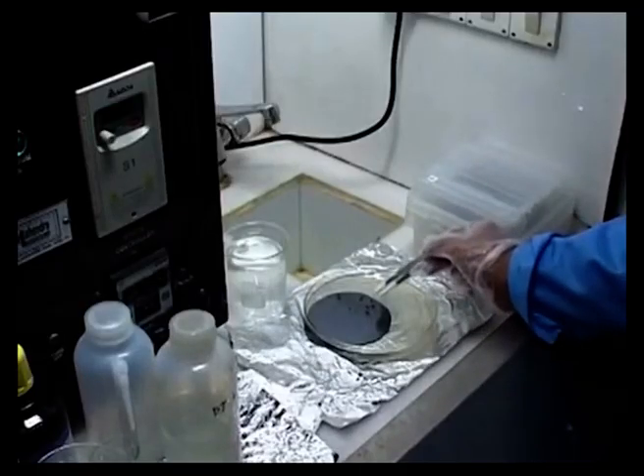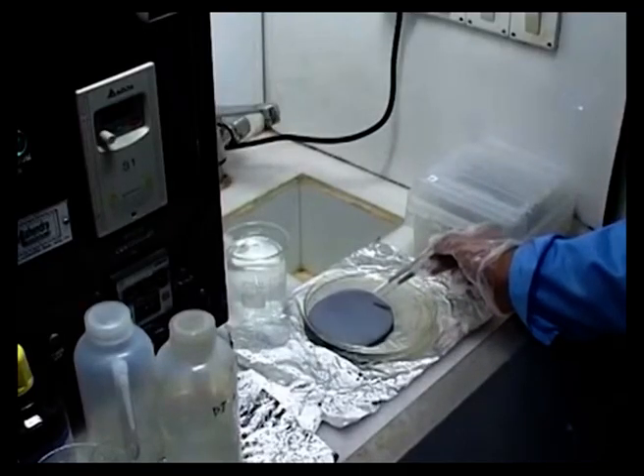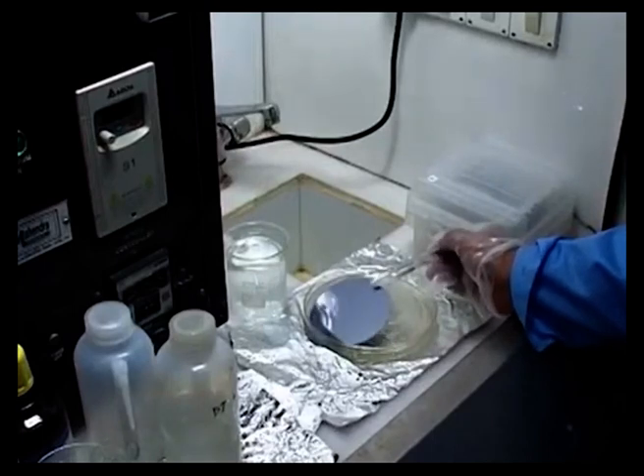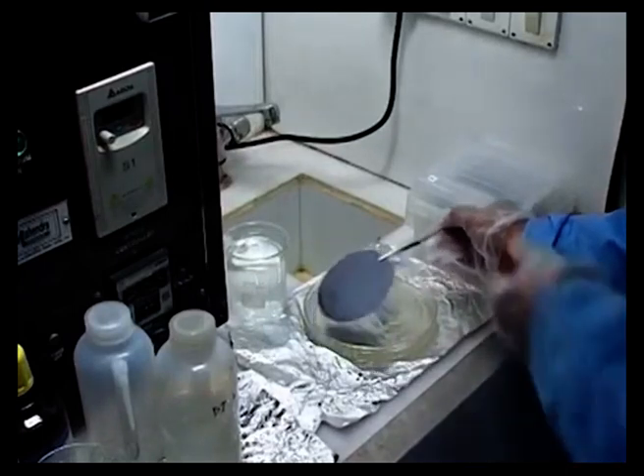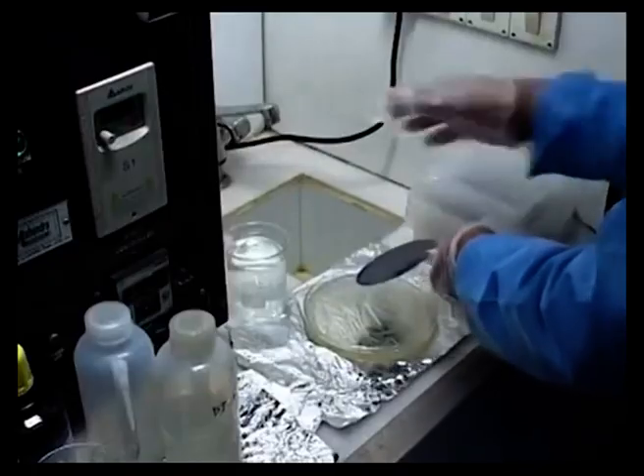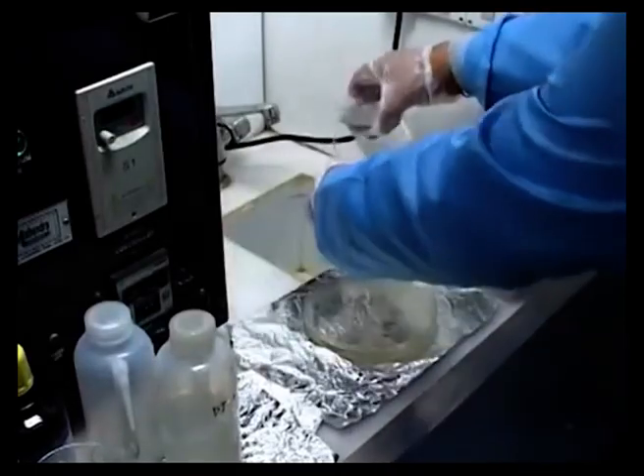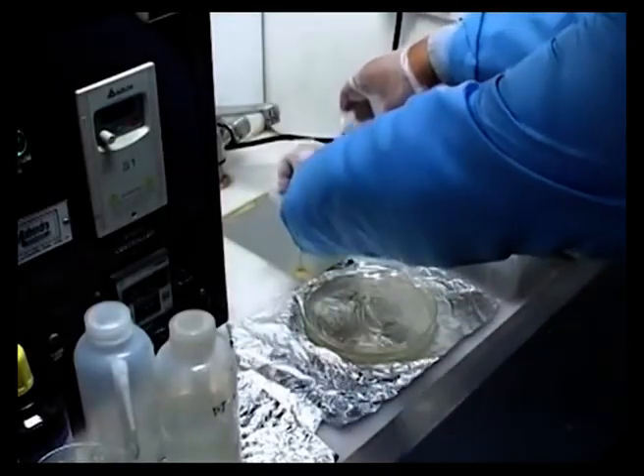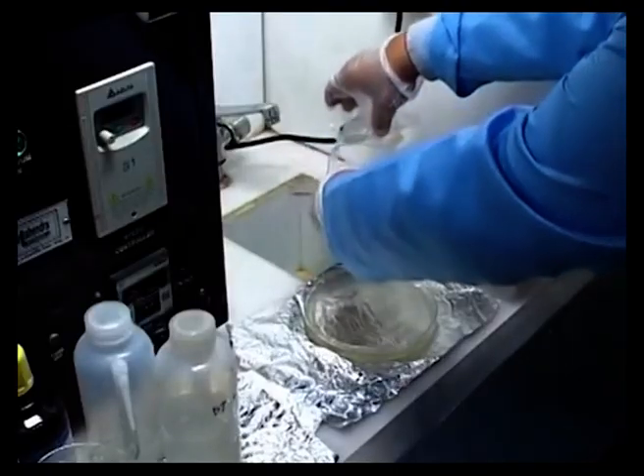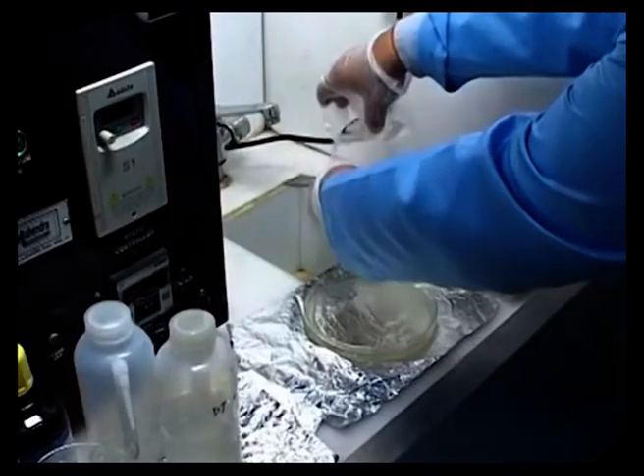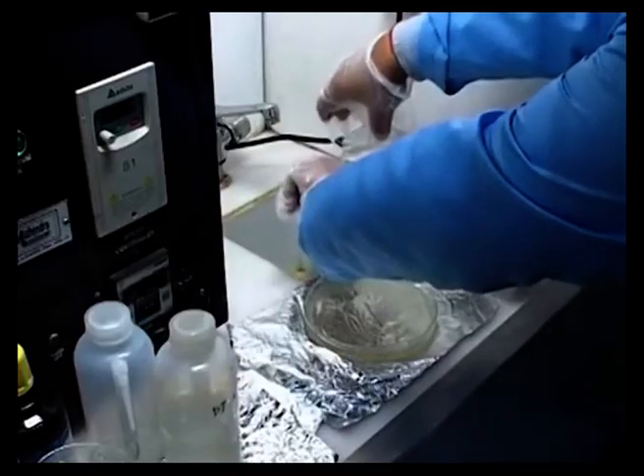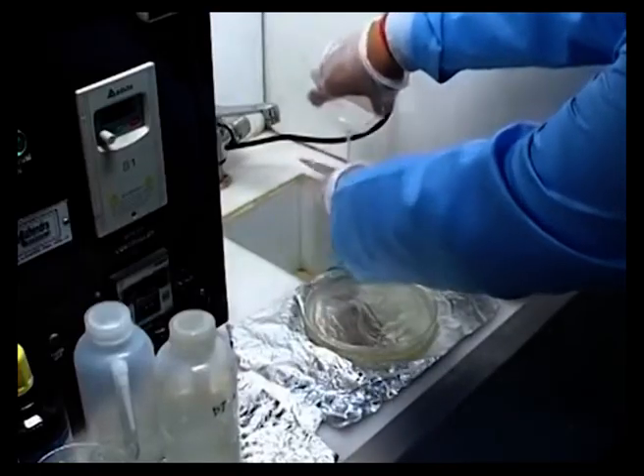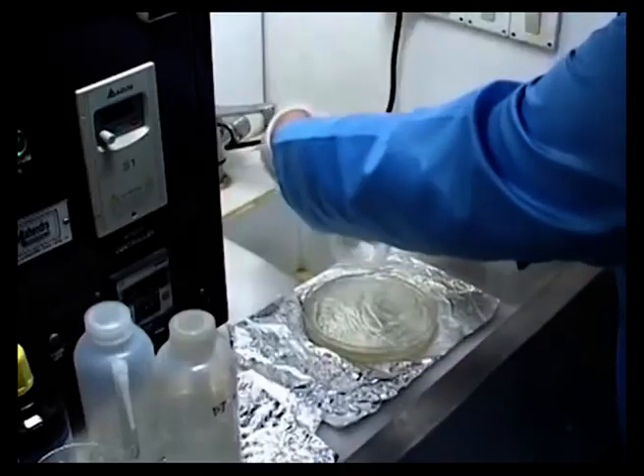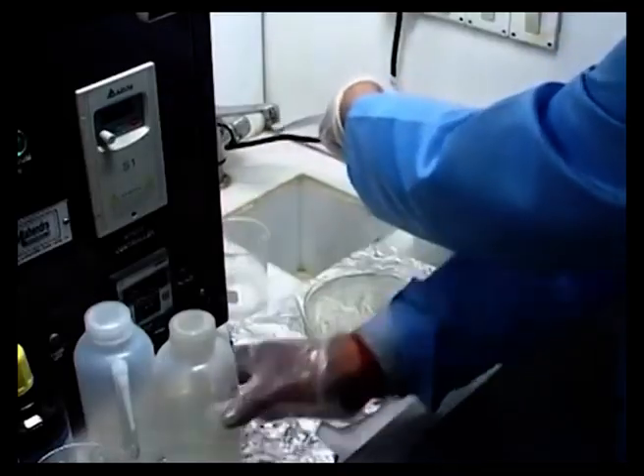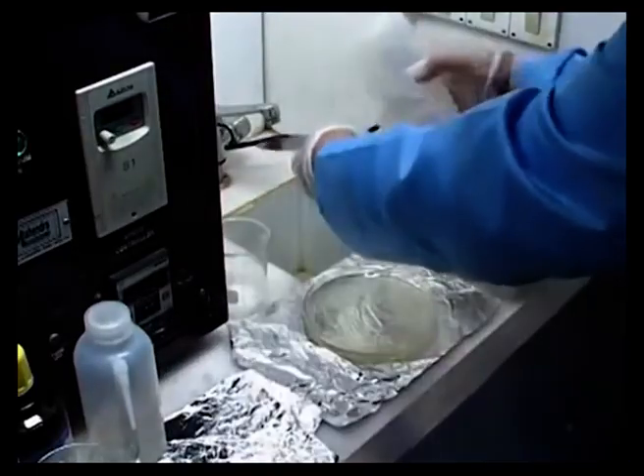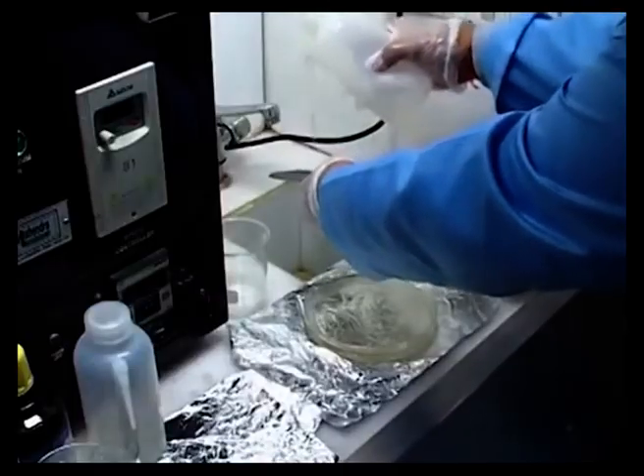So what we do is we basically pull it out very carefully, because essentially this is all acid coated now and one has to be very careful, and then hold this over this edge and rinse it inside this with water, and rinse it on both sides. As you can see, all the water should typically go and rinse all the acid off the surface of the silicon wafer, and essentially once this is clean, in the next stage what we do is we take this DI water and slowly rinse it on the surface of this particular wafer.